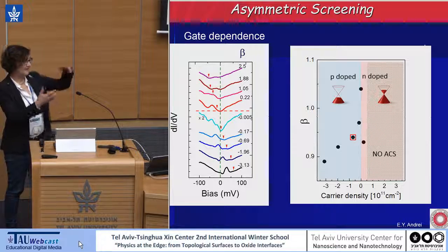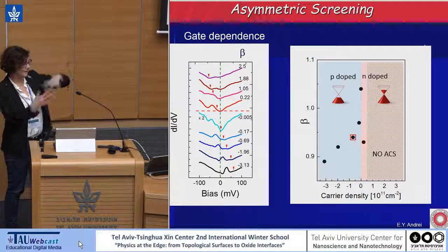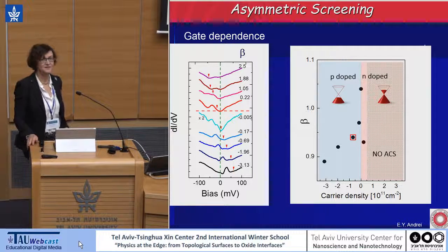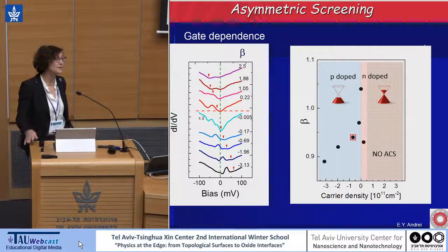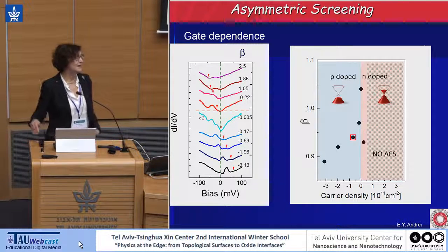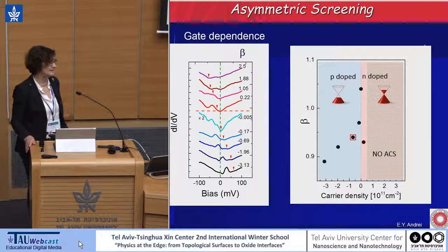So you take graphite, you exfoliate it, you blow it up, and then you irradiate it. This Manchester group irradiated it with protons, and they see it's magnetic. And they don't see screening, in contrast to what we see and in contrast to what transport people see. But if you see a magnetic moment, I'm not at all surprised. The only way not to see a magnetic moment is to have a perfect sample.